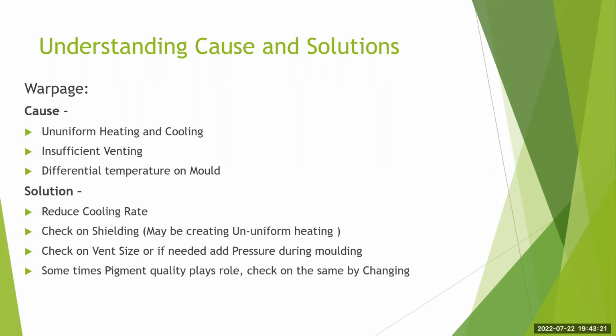Sometimes, uniquely, we have found that the pigment we are going to use plays a vital role. The reason is that the pigment is a non-polymeric material, and if there's a concentration of pigment in one area or the dispersion of pigment in the polymer is not there, it creates unwanted stress on the product, and that creates warpage. So you have to see these aspects as well.